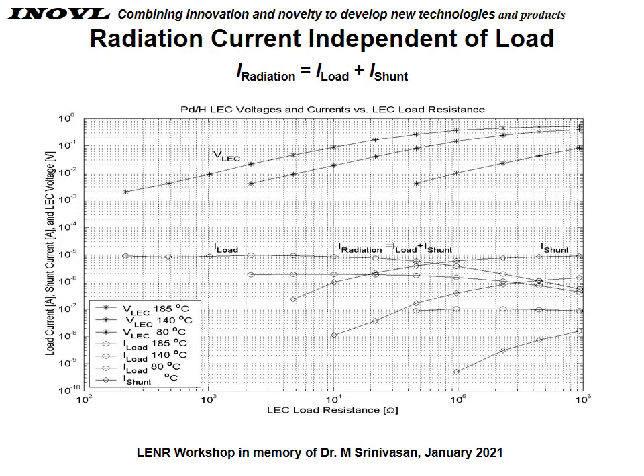So this plot shows the total current, where the radiation current is equal to the load current plus the shunt current. So now we have the I load, the radiation, and the shunt, which comes up as the load current goes down. Now I mentioned that this is 10 to the minus fifth amps of current, which isn't very much, but it's equivalent to 6 times 10 to the 13th becquerel. Recall that 1 curie is 3.7 times 10 to the 10th becquerel, so we've got 3 orders of magnitude more current here, more ions being moved, than what 1 curie of radioactive material will provide.